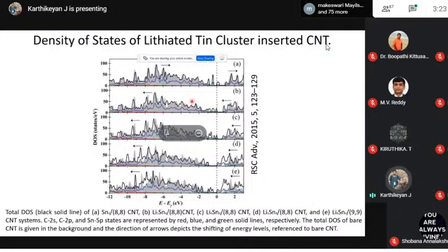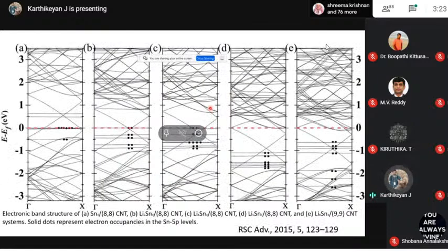So now we can check the density of states for lithiated clusters. When you add lithiated clusters in the CNT, you can see that the density of states is shifted away from the Fermi, especially the occupied levels are shifting away from the Fermi. That means it actually gives an electron to the CNT's band. That we can clearly see from the band structure calculation. So this is the band structure calculation of the pristine tin-CNT composite. Here I have shown the energy levels of tin clusters. The energy levels of tin clusters are very straight, so they are molecular levels. There is no dispersion of bands. Also, the dots are indicating the electrons filled in the tin p orbitals.